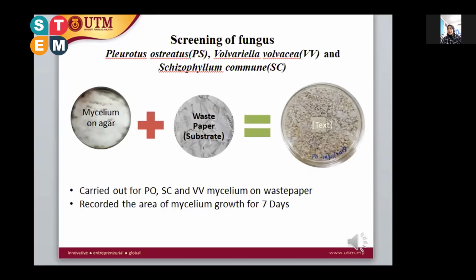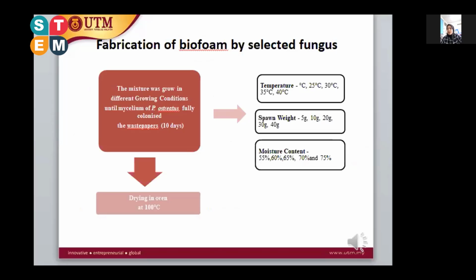Alright, here is the first step, where we screen the three types of fungus. The three types of fungus will be cultured for 7 days, and the area of mycelium will be recorded and compared. After screening the types of fungus, the best fungus will be chosen to optimize for the highest growth area. The best biofoam produced was investigated at different temperatures, spawn weights, and moisture contents, which highly affect the structure of the biofoam. The biofoam will be dried in the oven at 100 degrees for 24 hours.